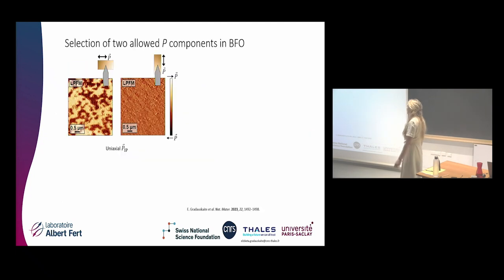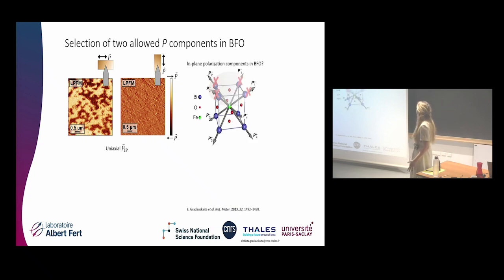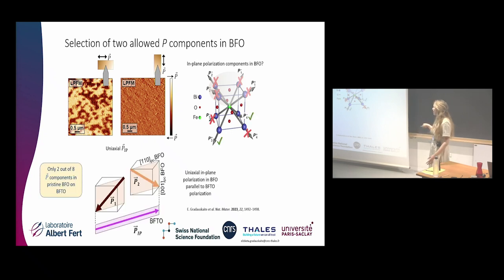So in the in-plane measurements of the PFM, we can see that we have 2 domain variants. In fact, we already knew that it's pointing downwards. And out of 4 remaining components, we know that we only have 2 components left. And these are polarization components that are collinear to the BFTO polarization below. So it looks like the strain, and also the electrostatics, is somehow enforcing this very unusual selection of ferroelectric polarization variants and domain variants.